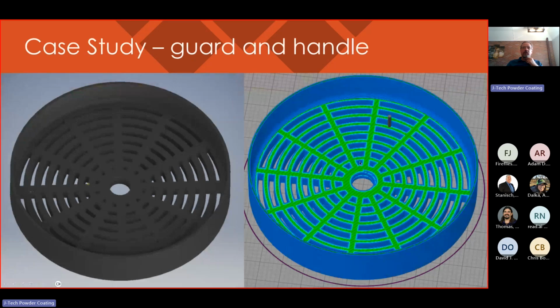This is the mating part with that. The grill slot profiles and the fine thread required a lot of passes, but it's very printable with a fine resolution. But one of the requirements was to print a pair in less than 2 hours. These initial designs took about 10 hours to complete. So this was a challenge. You know, we couldn't speed up the printing enough to meet the print goal.